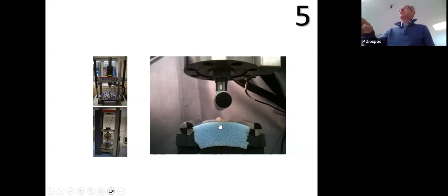Now, believe it or not, that's what will happen in your femur when you sit in the car, you have a car crash, and your knees hit the dashboard. Only few cars carry airbags to protect the knees. But when your knees hit the dashboard, the femur gets into compression, experiences up to 7,000 to 8,000 newtons, and believe it or not, it fractures into thousands of little fragments. It's a catastrophic failure in the middle of it because it bends under the compression. And that's the stored energy, phenomenal energy.